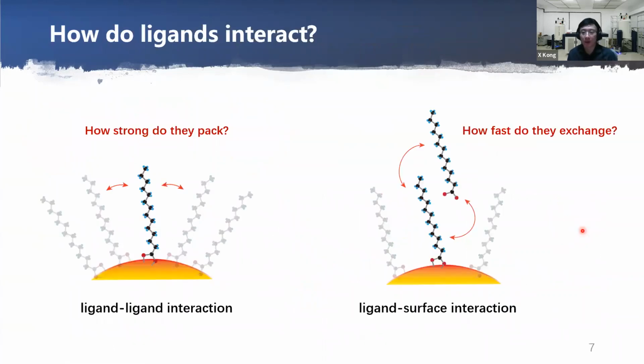Besides the coordination and the partition morphology, the interactions between ligands are also very important. Today, I'm going to introduce how we calibrate interactions. Here, we look at two possibilities. One is the interaction between the ligands themselves, called ligand-ligand interaction. These are dispersion interactions between the hydrocarbon chains. These ligand-ligand interactions affect the packing strength in the solid phase. The second is the interaction between the ligand and the surface of the nanocrystals. The ligand-surface interaction affects the dynamic equilibrium of ligand exchange when the nanocrystals are in solution.